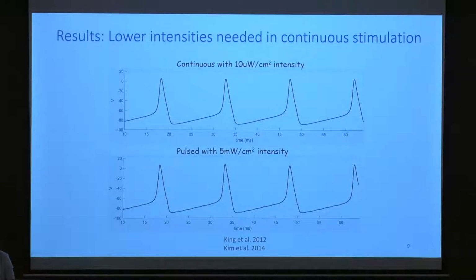So, to begin with the results, the most relevant result of our model to date is that we noticed that continuous ultrasound stimulation requires much less energy values to cause a modulation in the action potential. The graphs show the action potential in the membrane as a function of time. If we compare both graphs to get the same response, for the continuous stimulation, we actually required 10 microwatts per centimeter squared of acoustic intensity, while for the pulsed, we needed 5 milliwatts per centimeter squared of acoustic intensity.